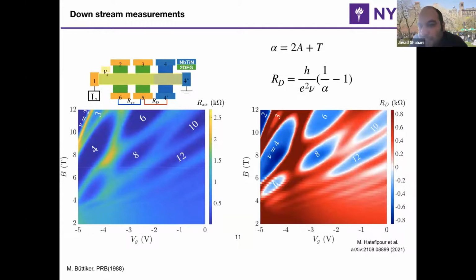But now if you look at the color map values of the resistance, now we are measuring almost minus 0.8 kilo ohm, right? It's not supposed to be minus 0.8 kilo ohm. I would expect like 0, like the left side. Or maybe I don't expect it if I can allow for these Andreev reflections. And the model that we have used in our paper mostly is basically just a modified Büttiker formula that, instead of having just normal reflection and a normal transmission, which in a usual case would be all R plus T equal to 1, you allow for this A to be the Andreev reflection. And then this parameter alpha comes into the game.